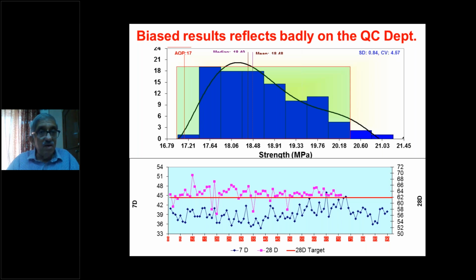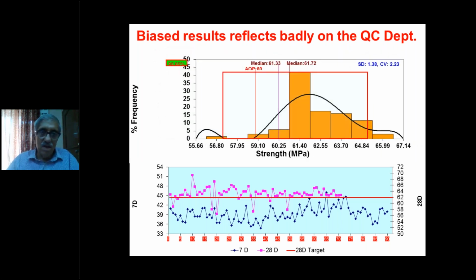We used to test quality of cement at 3 days, 7 days, and 28 days. And 3 days, 28 days results were given as the quality parameters which the quality control people had to achieve. And sometimes biased results were observed and confirmed, because we also saw that whenever the 7 days results were low, 28 days results were higher, which can never occur, and vice versa. So we have to have a proper reporting system, unbiased, which shows a bell-shaped curve like you see on the figure.